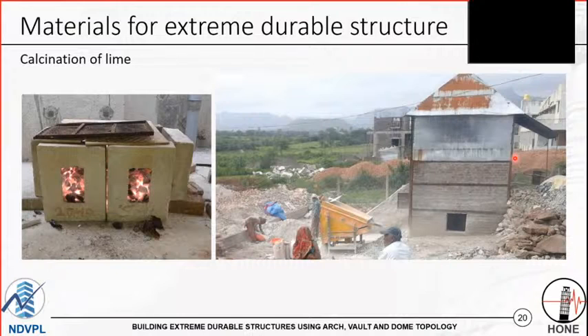Whereas if you use hydraulic lime, hydraulic means one which can set under water. So if you can get lime which has an impurity of silica, you can use it for construction. And the strength you can get is also very significant. For 30 days strength, I will not focus much, but 90 days strength with lime we are getting above M50 for mortar. That's a significant strength we are able to achieve on our sites and in our lab.